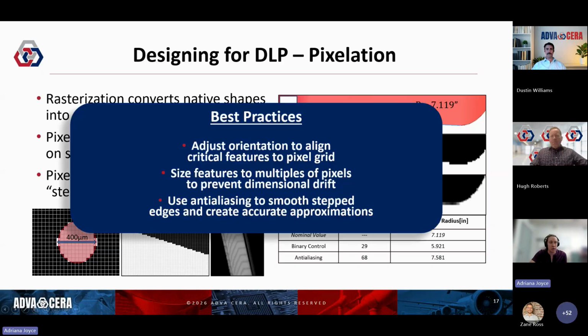But we've got a couple tools that we can use to work around these limitations of the technology. So if we know that we have critical features, such as a straight edge that needs to be straight and smooth, we can align that to the pixel grid. So that one becomes smooth, and then less critical features can suffer that stepping effect. We can also size features, if we're designing the part from the beginning, to multiples of the pixels. Taking into account the scaling that we have to do for the shrinkage during debinding, we can make features pixel sizes and avoid that dimensional drift that occurs when a repeated feature or a repeated part doesn't stay constantly aligned with the pixel grid. There's also anti-aliasing.